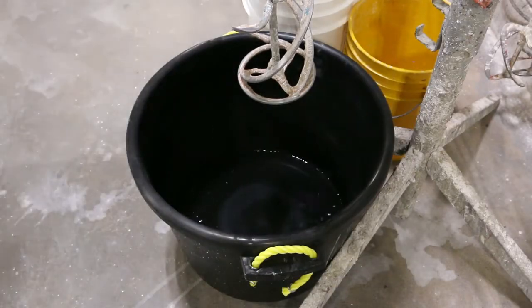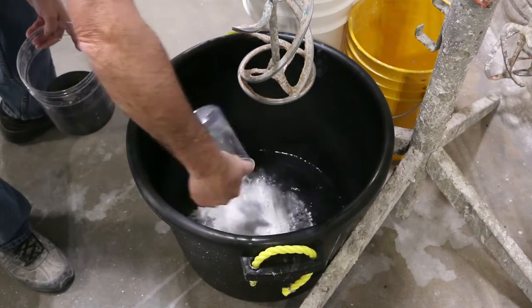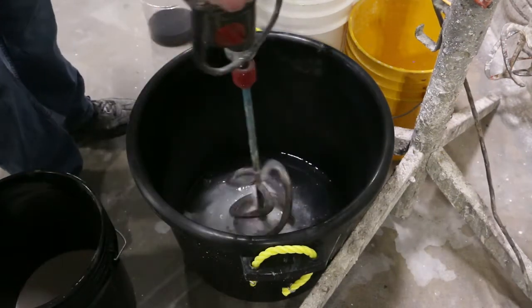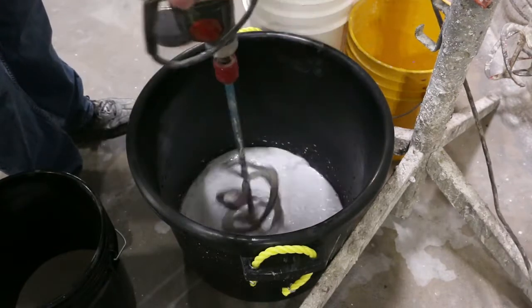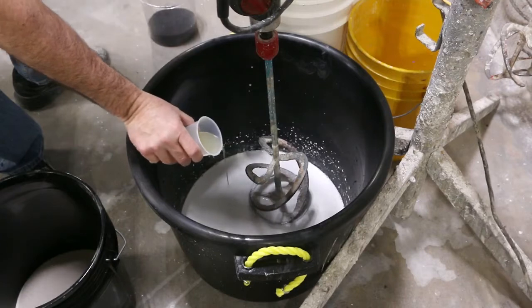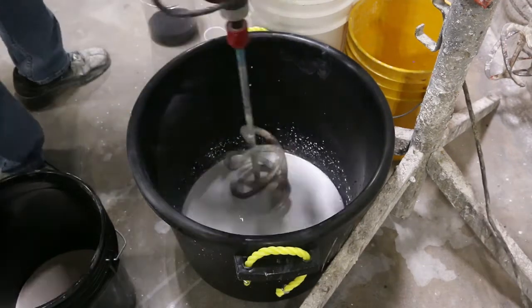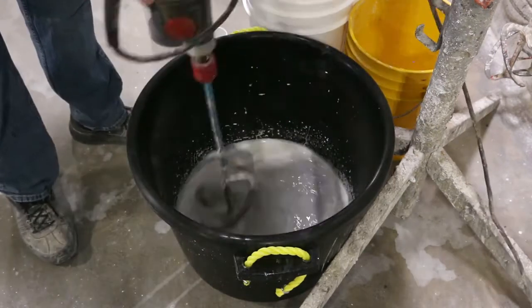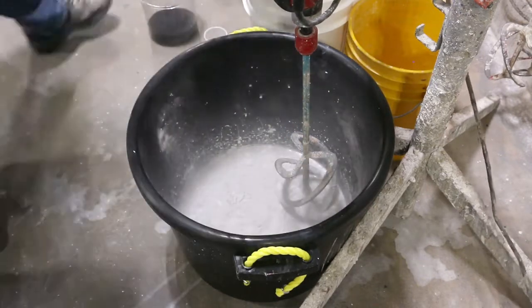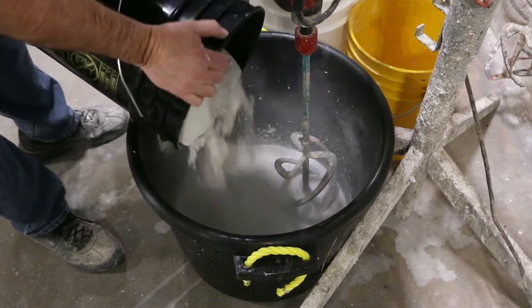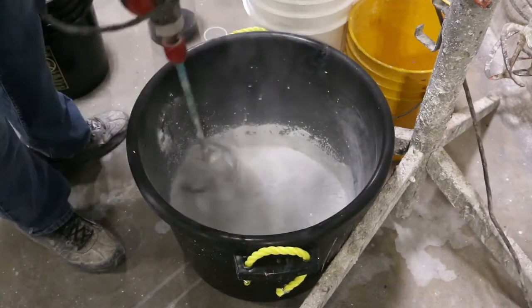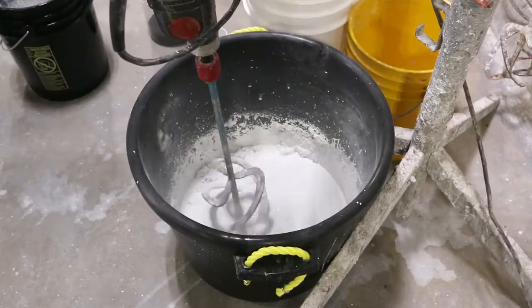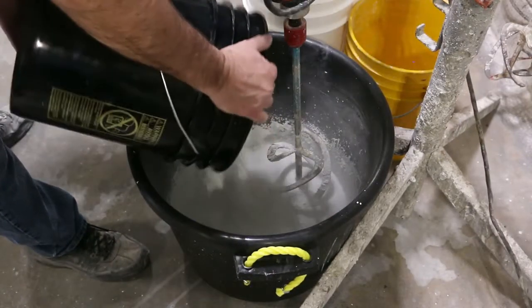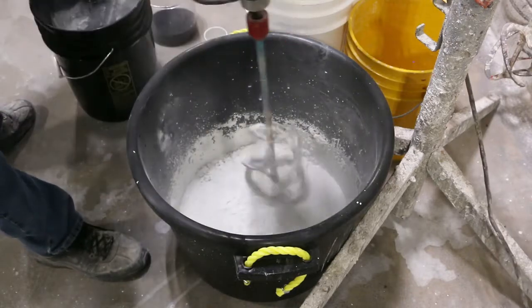Start by adding chilled water to a clean mixing vessel and add titanium white pigment to the water. Mix well. To this I added 2 ounces of water reducer 420 and blended well. Add the 30-60 mesh sand and blend well. To this add the Buddy Rhodes GFRC admixture and half of the Portland and blend well. Continue incorporating the remaining Portland, stopping to add more water reducer 420 as needed.